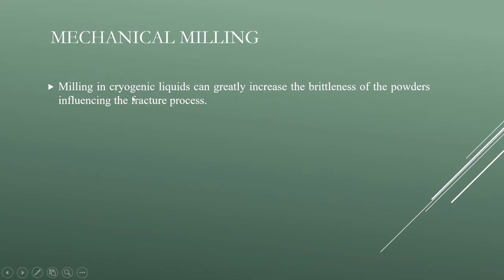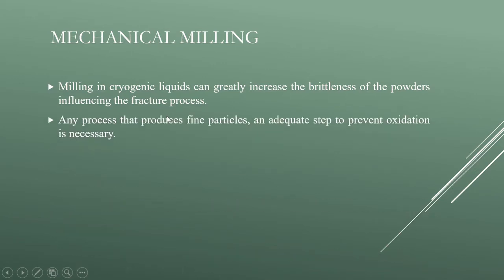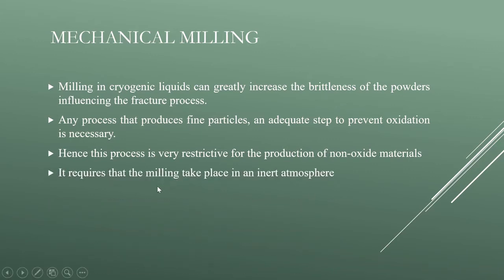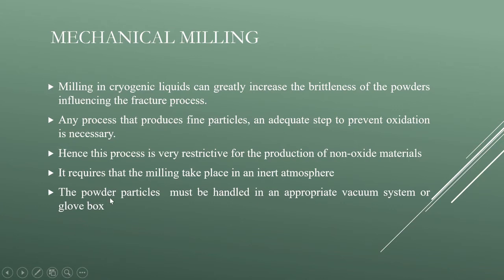When milling is done in cryogenic liquids, it can greatly increase the brittleness of the powders, which also influences the fracture process. Any process that produces fine particles requires steps to prevent oxidation; hence this process is very restrictive for the production of non-oxide materials. It also requires that milling be carried out in an inert atmosphere, and the powder particles must be handled in an appropriate vacuum system or glove box to prevent oxidation.